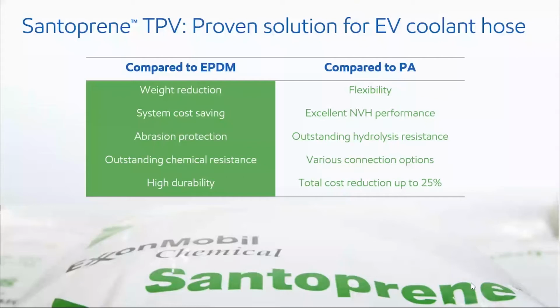Now, if we look at the comparison with polyamide, polyamide hoses are very, very stiff hoses. So flexibility is not possible with polyamide hoses, whereas Santoprene hoses can be made flexible as well as stiff. So we have the choice. Santoprene TPV has excellent NVH performance, low noise, vibration, harshness. It has very good hydrolysis resistance for the coolant hose applications. There are a lot of connection options. We can use either clamps or quick connectors, whereas with polyamides, we have to use quick connectors, which is again a costly affair. And the total cost reduction possible is around 25% by using Santoprene TPV in place of a polyamide hose. So this clearly shows that Santoprene TPV is the material of choice for EV coolant hose application, considering all the properties and all the superior performance that it offers to the segment.